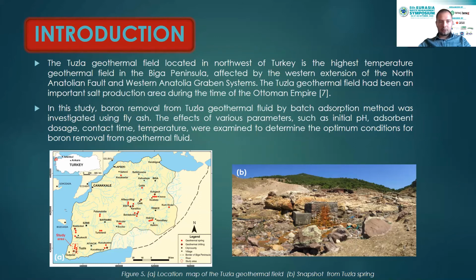In this study, boron removal from Tuzla geothermal fluid by the batch adsorption method was investigated using fly ash. The effects of various parameters, such as initial pH, adsorbent dosage, contact time, and temperature, were examined to determine the optimal conditions for boron removal from geothermal fluid.